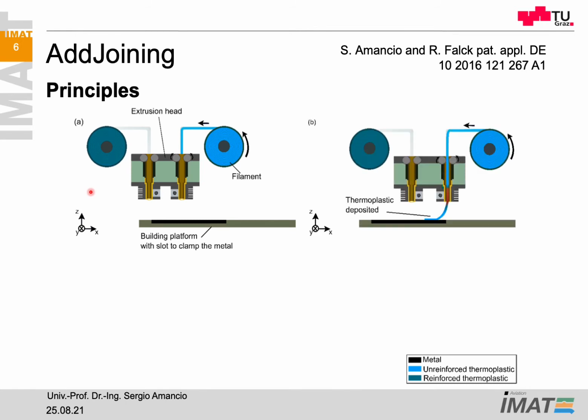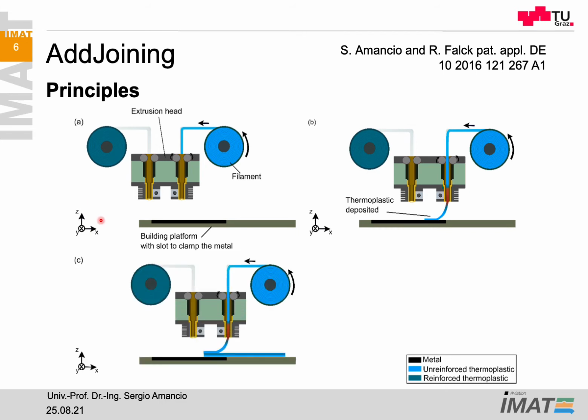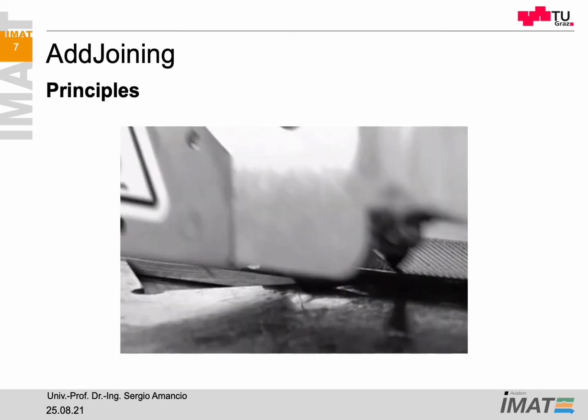The first step is to deposit a so-called coupling layer. It's a very thin layer that has a similar function as an adhesive, but it's composed of the same composition of the fiber reinforced composite. This is placed on top of the metal, and then the process continues, alternating the deposition of fiber reinforced and unreinforced layers until you get an overlap joint or an overlap structure where you have a composite-like structure deposited on the top or around the metal part. I would like to show a short movie showing the fabrication of the specimen I'm going to present.